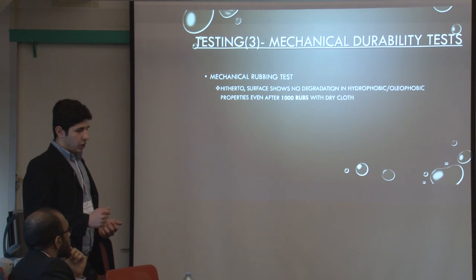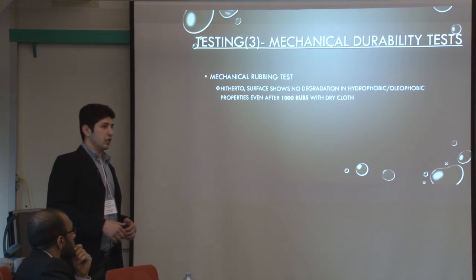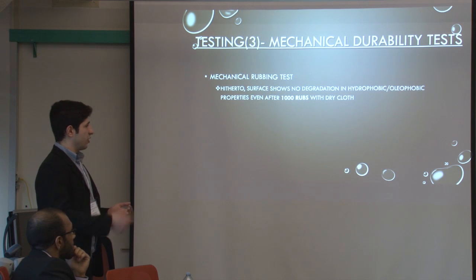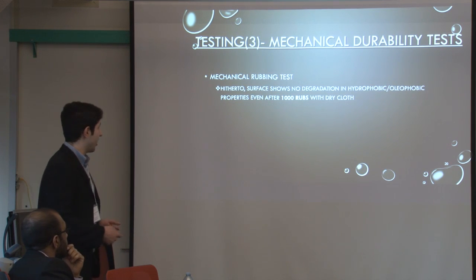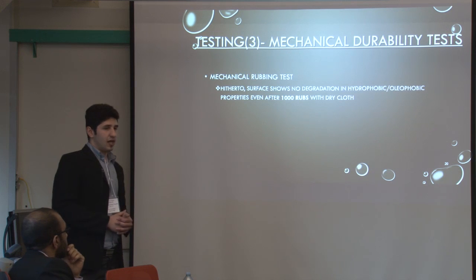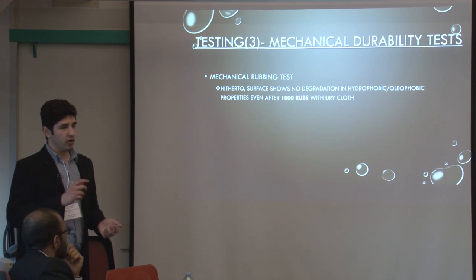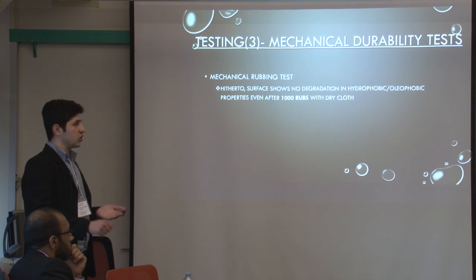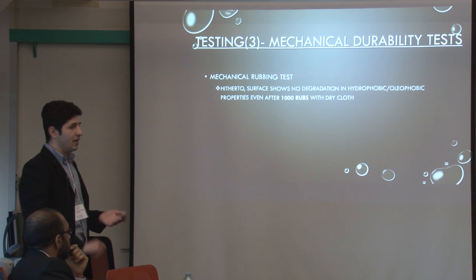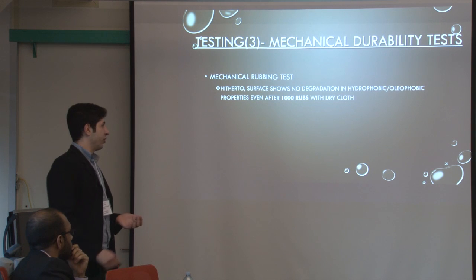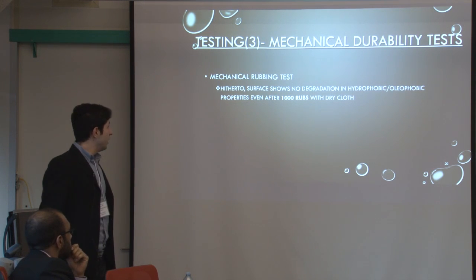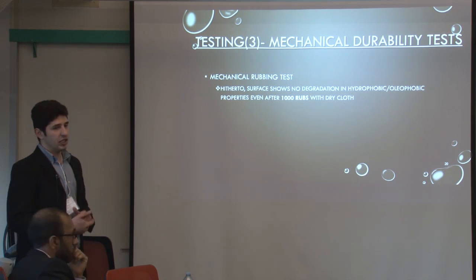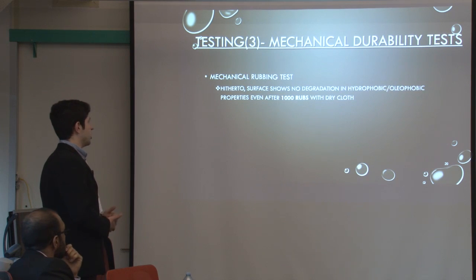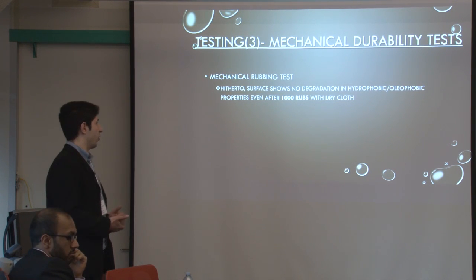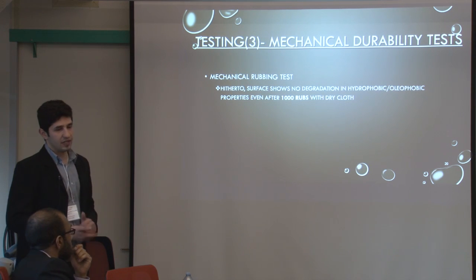At the end, we need to make sure that our design is stable for use over time, since the customers are going to be using this over and over for a longer period of time. One of the industry standard tests is the mechanical rubbing test, where you use a dry cloth and rub the surface as many times until you see deterioration in its properties. We went up to 1,000 rubs without seeing any changes in the oleophobicity or hydrophobicity of the surface. Same goes for the transparency.